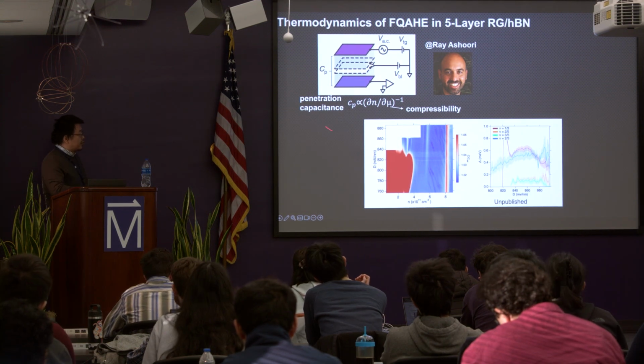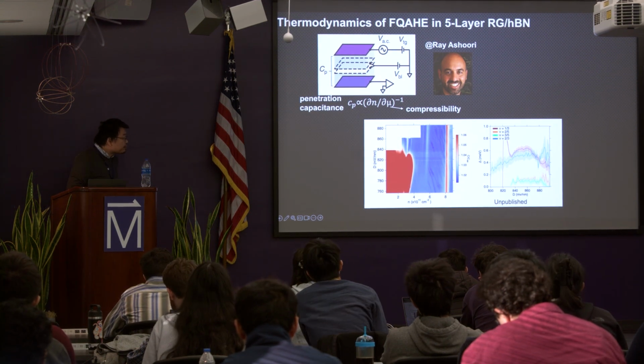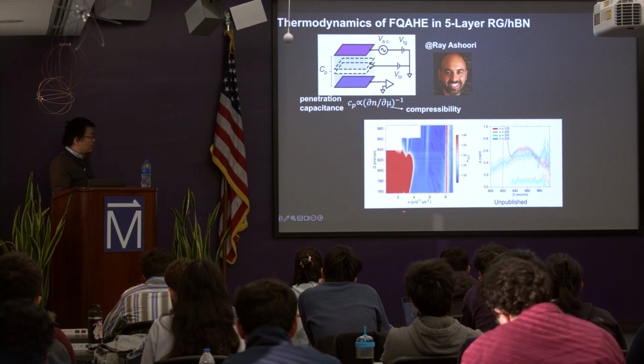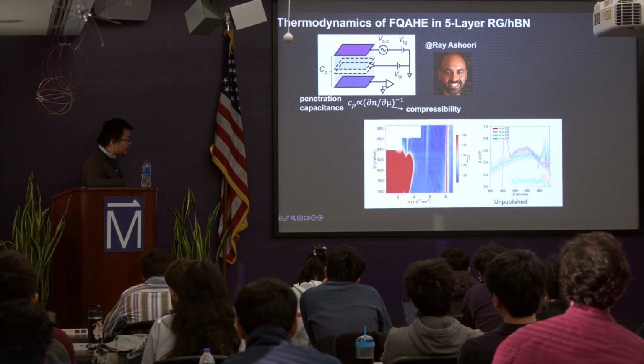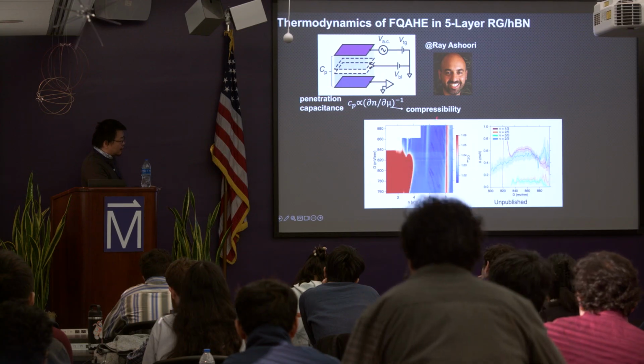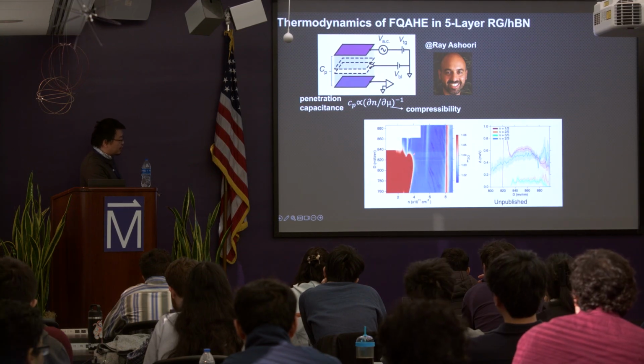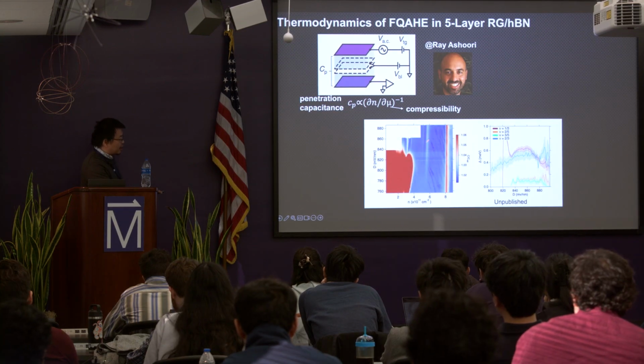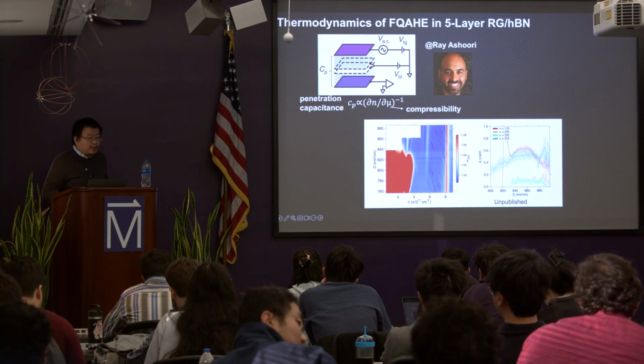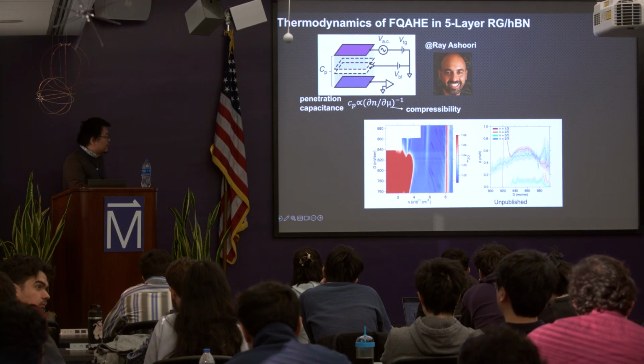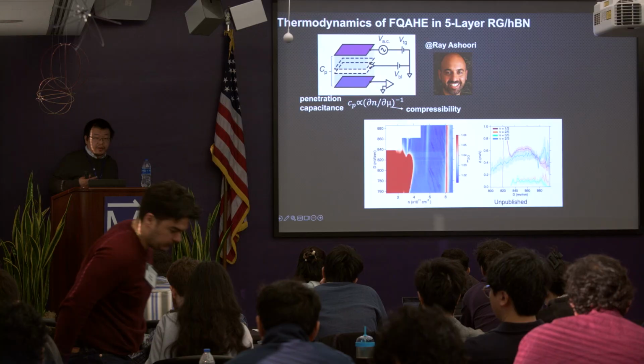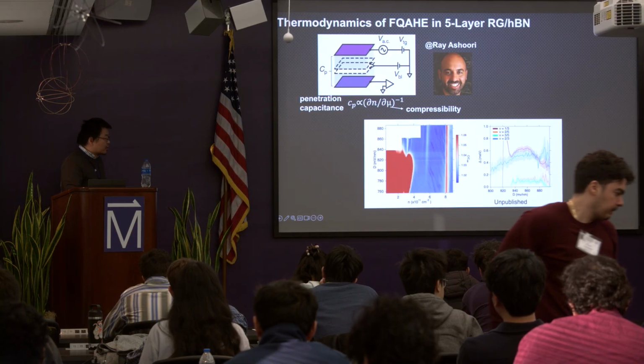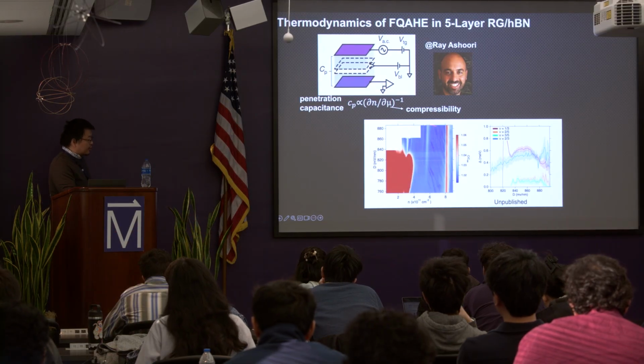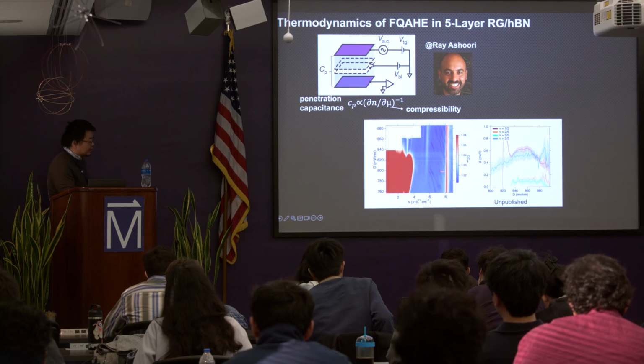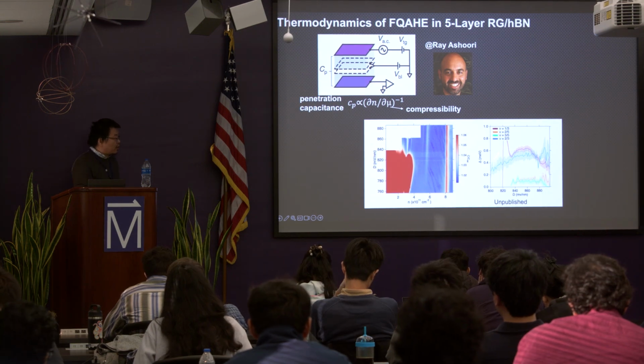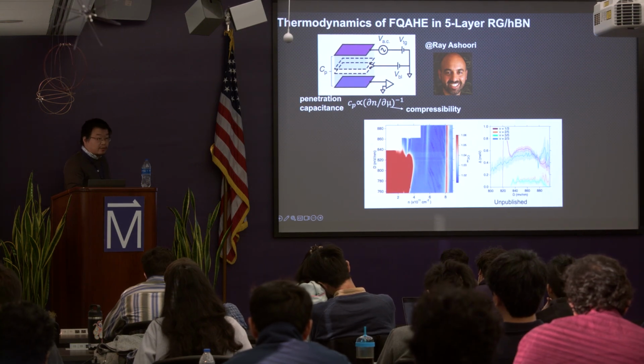This is actually work done by a collaborator, who checked an additional sample. Those white lines are 1/3 and 2/3, and there are more faint lines at 2/5 and 3/5. When they measure the penetration capacitance, which is proportional to the inverse of the compressibility, they can make sure that at least all these fractional states and also the inter-states are gapped. They can also extract the gap values of those states.